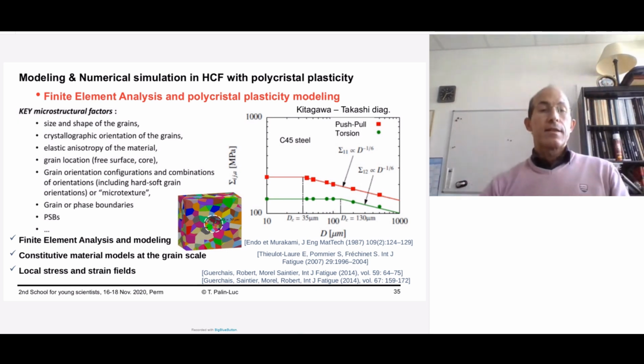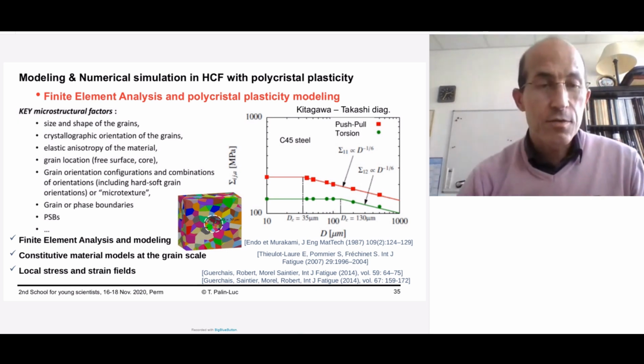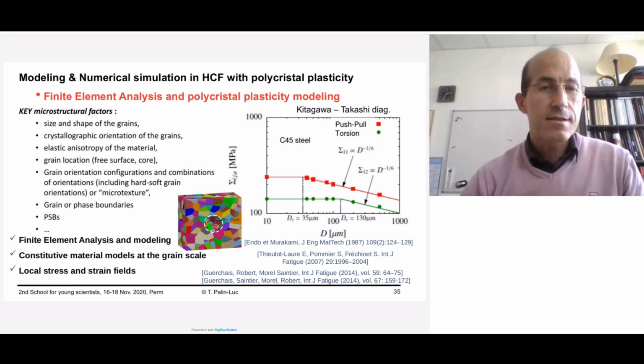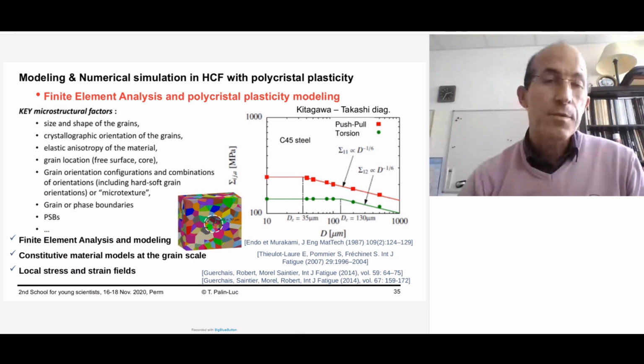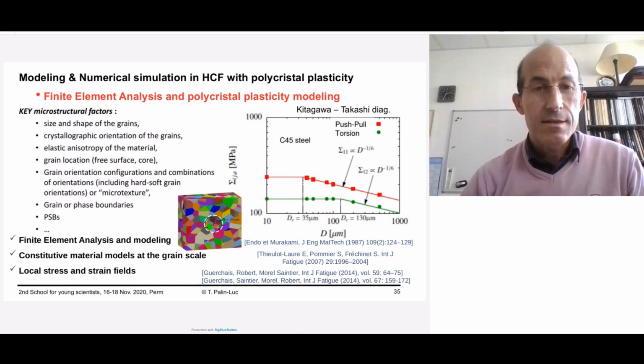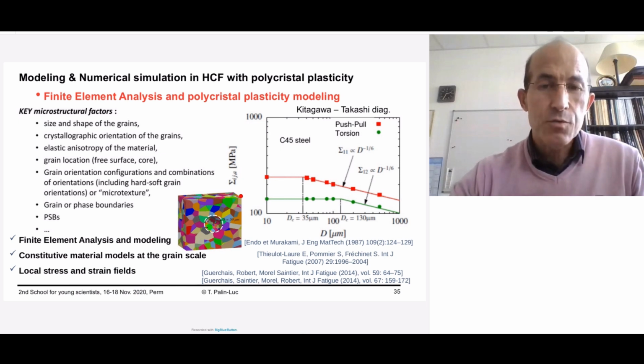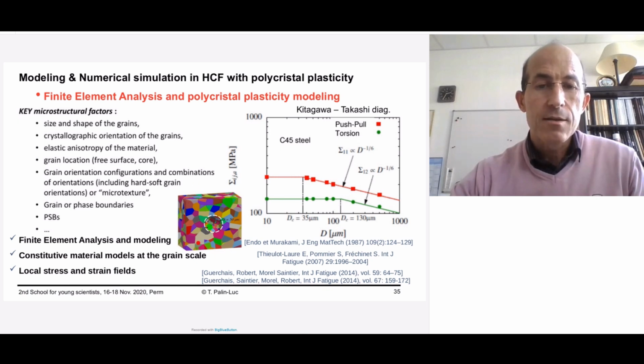This fatigue strength computation can also be done by finite element analysis, and especially for approximately 10 or 15 years, by finite element analysis at the grain scale. We named that polycrystal plasticity modeling. So the interest is to be able to reproduce, like here, a representative volume element with the grains.